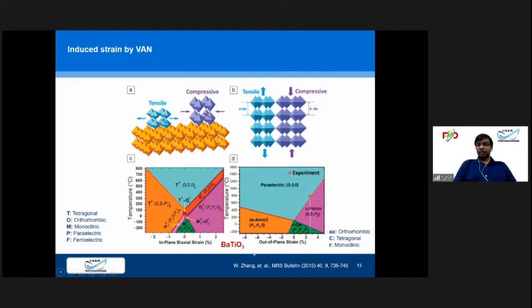So by that, we can create a different kind of strain. This is in-plane strain, like in the A and B direction, and this is out-of-plane, that is the C direction. So by this vertically aligned nanostructure, we can create three-dimensional strain on the column or the matrix. And these materials also need to have a Young's modulus close enough to create pressure on each other. That is another critical point we need to consider, but I'm not going to talk about that because it will make things more complex.